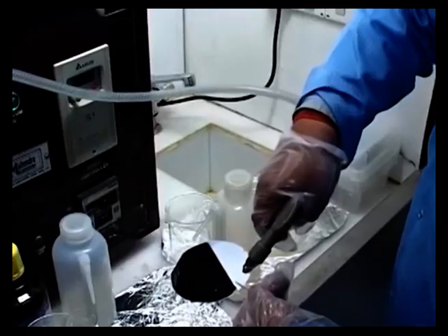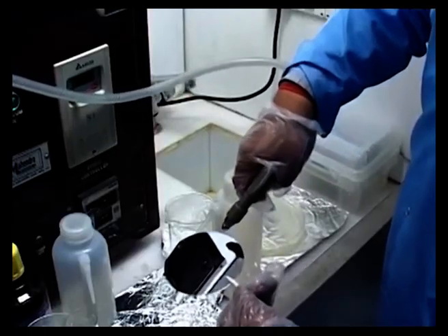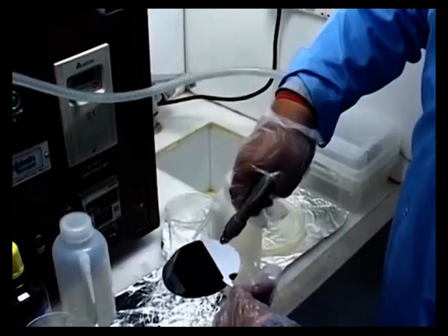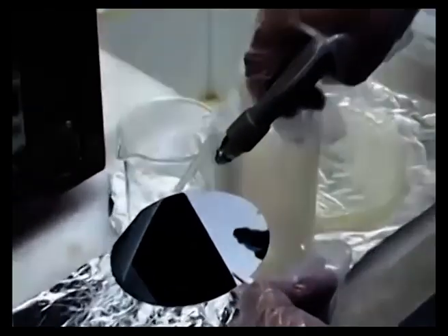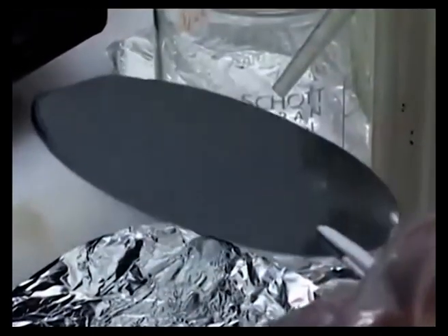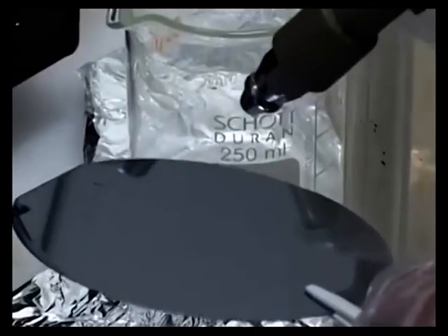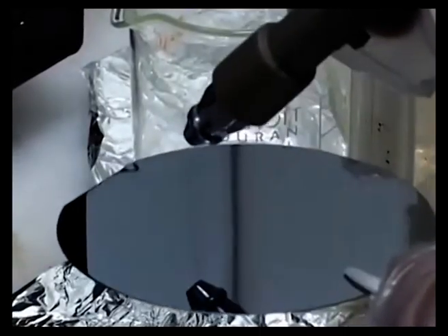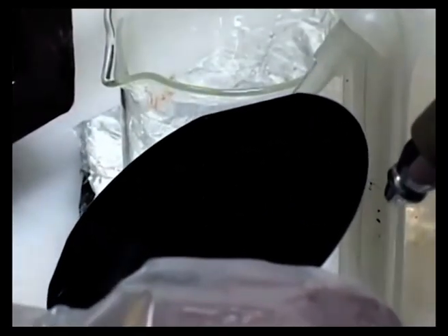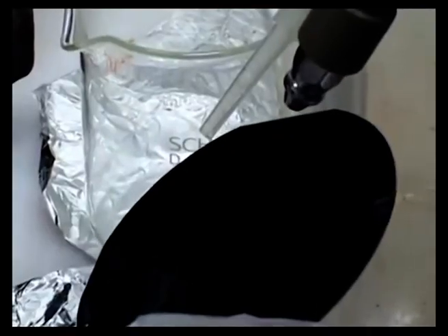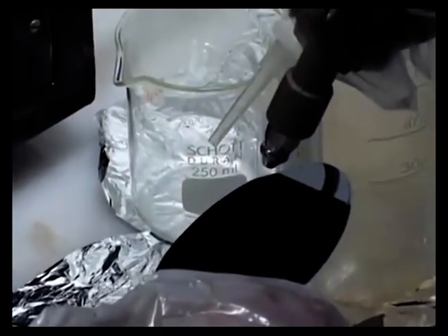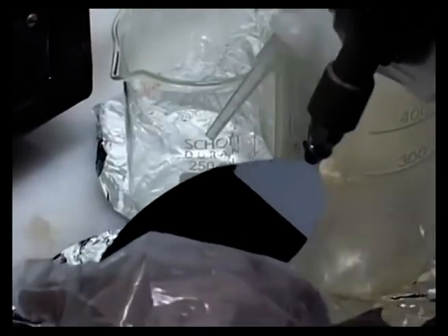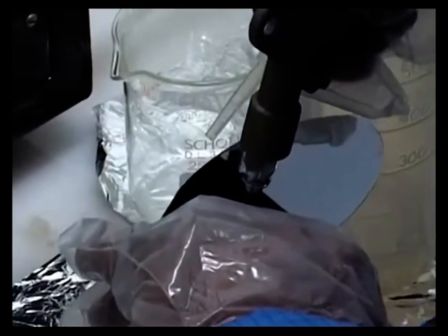Okay, so essentially you have to move this thin film of water in the clean hood away from the side, so that you are actually left with a clean surface of the wafer, a clean shiny surface of the wafer, and there should not be any water drop in this manner on the surface. Typically all the water film should go away from the surface. Similar cleaning has to be done for the reverse side, and I am going to do that, as you see here, seeded from the compressed nozzle side towards the other side, and it is then rinsed off the surface by squirts of compressed air, as you can see. Okay, so this now really is a super clean surface for lithography to take place.